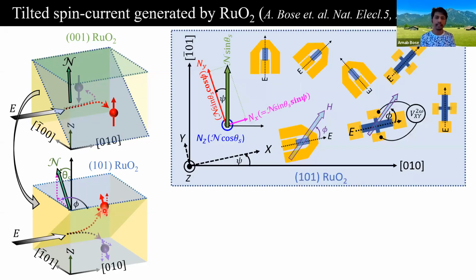For this, we patterned devices such that we can apply current along different crystallographic directions, as shown here. We fabricated devices for the SD-FMR and second harmonic Hall measurements, as shown here. There are two important things to note. First is that here for the 101 plane, we have canted Néel's vector, meaning it will have projection of this Néel's vector in the plane and out of the plane. So this is a projection of the Néel's vector out of the plane.